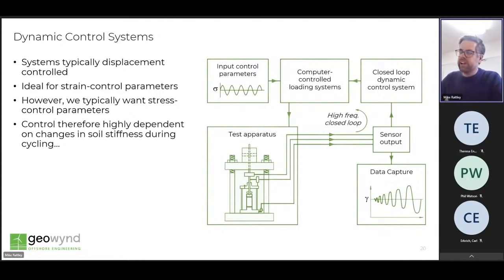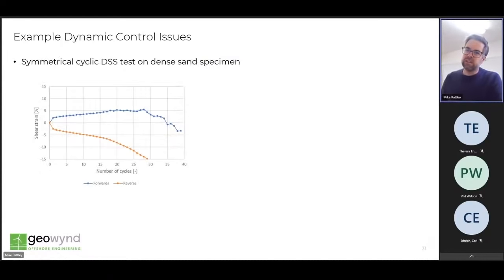For example, to generate S-N curves describing strain accumulation under constant amplitude cyclic stress. And this means that the control feedback of the system is indirect, and the stability of the test control actually becomes highly dependent on changes in soil stiffness occurring during cyclic loading. And as we've already seen, and as we've intimated already, those changes in stiffness can be significant.